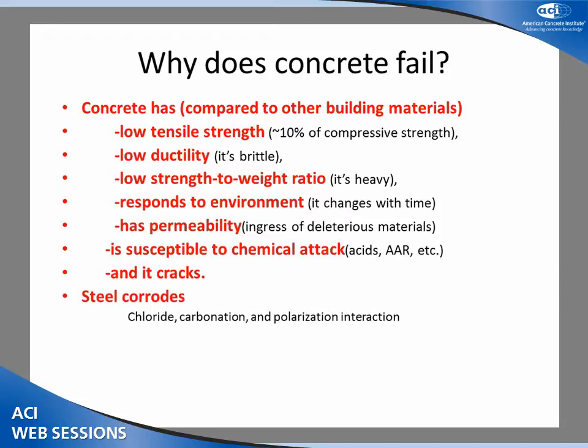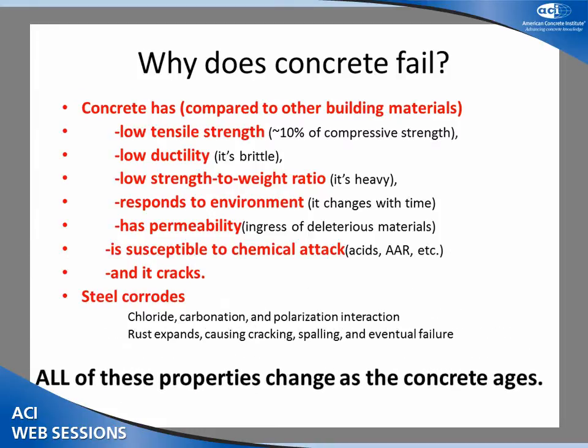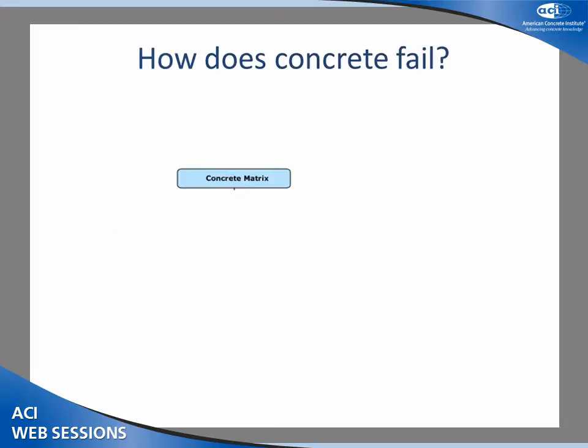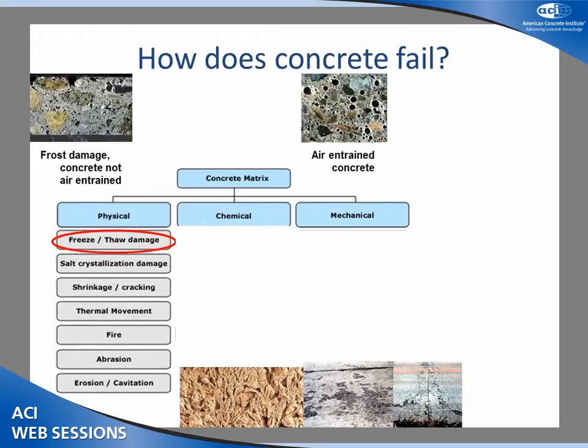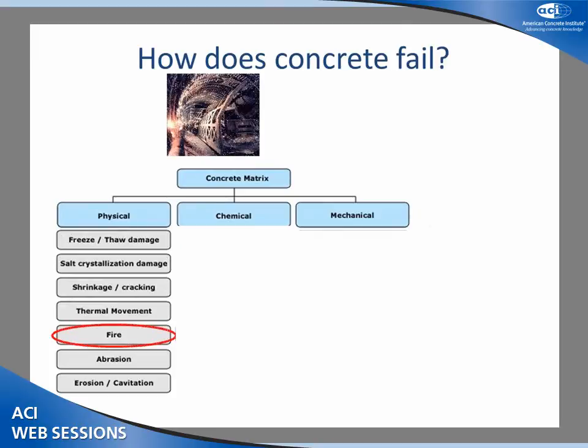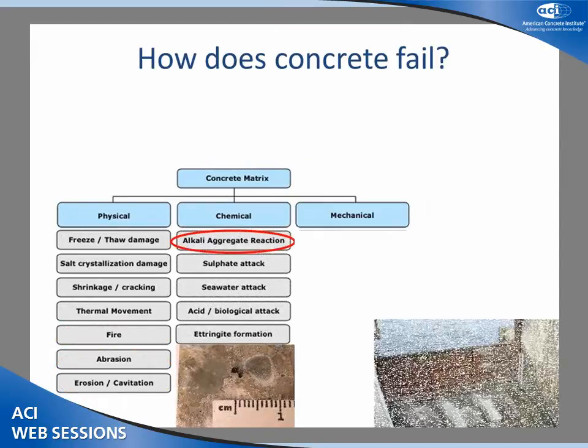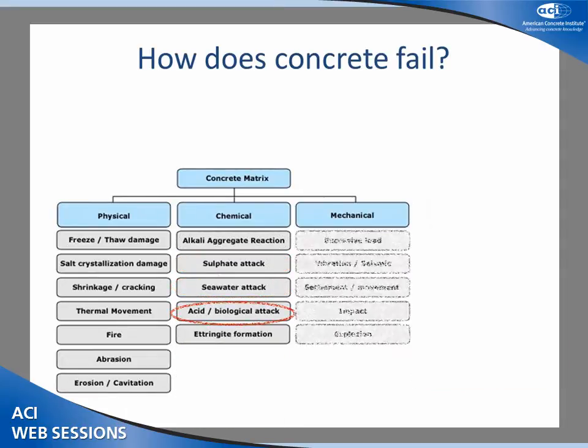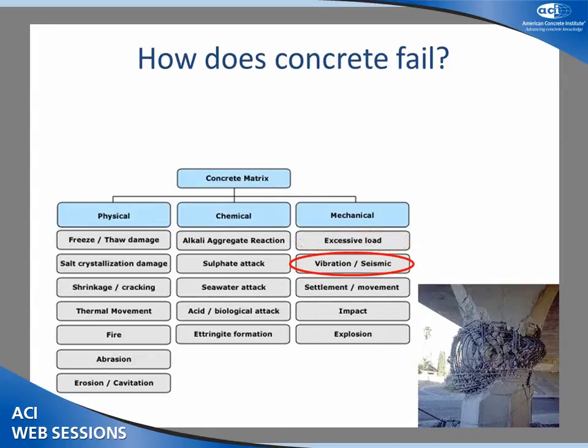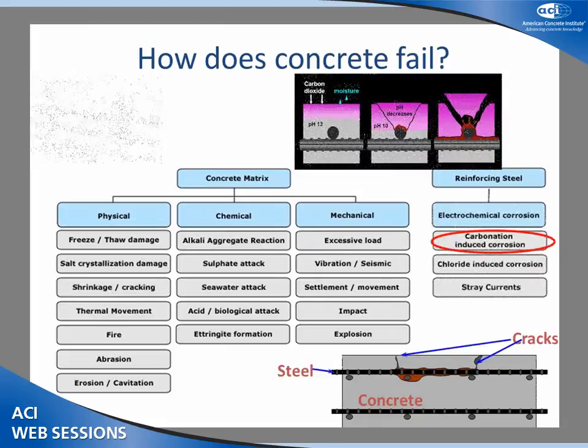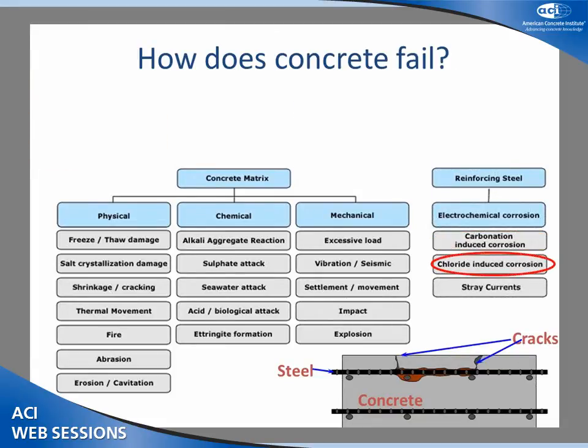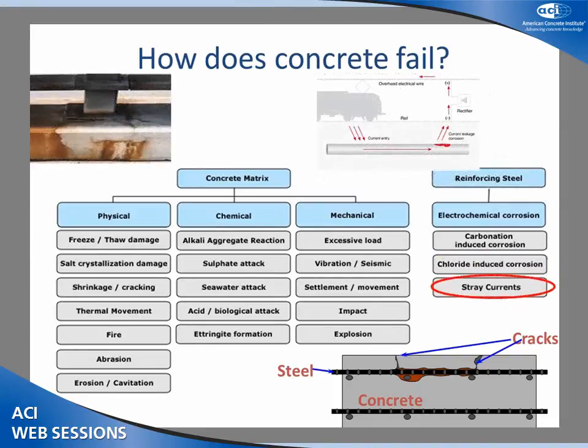Furthermore, steel corrodes. Anytime you put steel in a concrete structure, you're basically installing a time bomb. Sooner or later, that steel is going to corrode. That's just thermodynamics. It may be 100 years from now, it's going to rust. When it rusts, it expands, and all of these properties change as the concrete ages. A little more detail. We've got freeze-thaw damage, salt crystallization damage, shrinkage and cracking, thermal movement, fire damage, abrasion, erosion, cavitation, alkali aggregate reaction, sulfate attack, seawater attack, biological attack, excessive loads, vibration and seismic incidents, impact, explosion, reinforcing steel. 3 primary mechanisms: carbonation-induced corrosion, chloride-induced corrosion, and stray currents, or polarization changes in the steel. All 3 of these work together synergistically as well to make the steel rust.